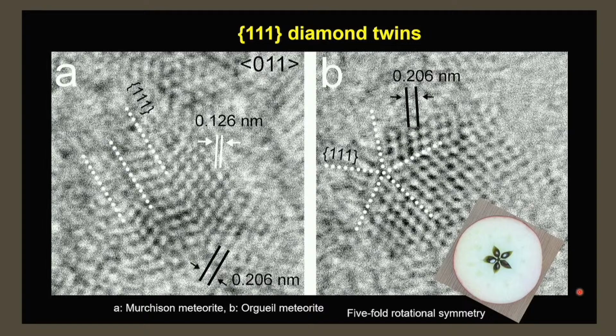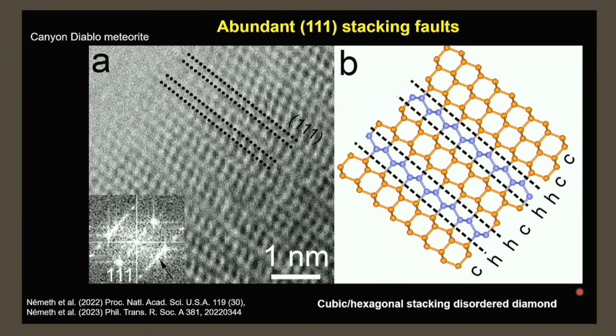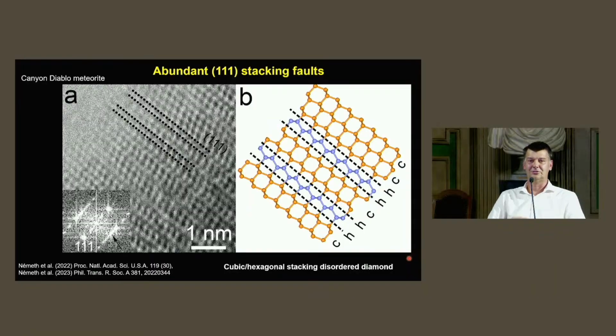Anyway, when I was talking about investigating this Canyon Diablo material, which was called Lonsdaleite, when using transmission electron microscopy, we found that there are abundant defects within the cubic diamond layers. But the point I would like to make is that these hexagonal diamond layers occur as up to 2-4 layers. So we would rather say they are defects within the diamond lattice, or in fact they form a unique material. On panel B you could see the structure of the material, and we gave it a unique name, the cubic hexagonal stacking disordered diamond.